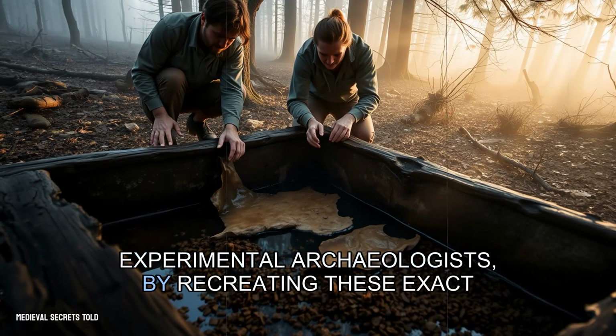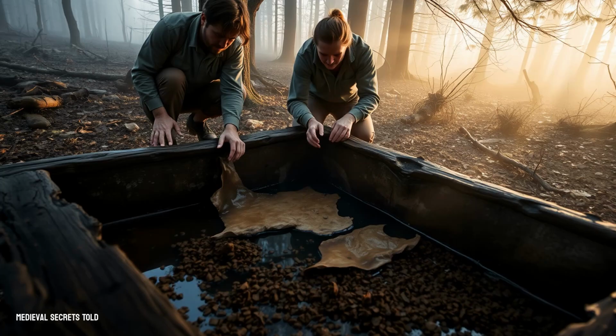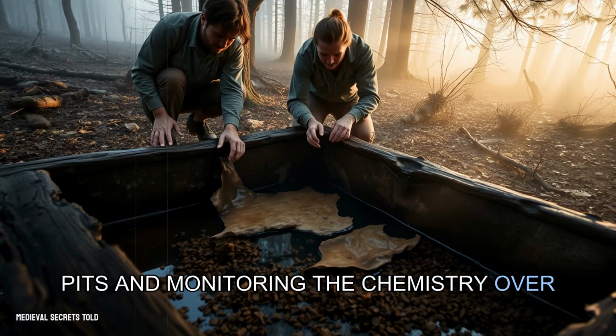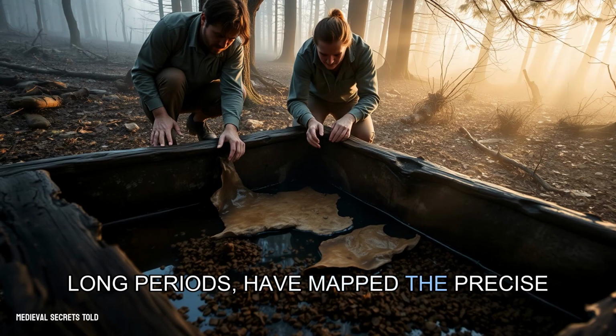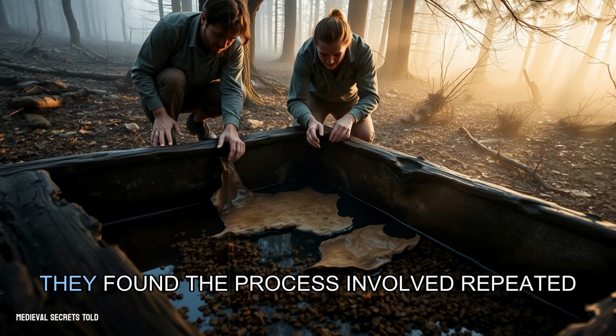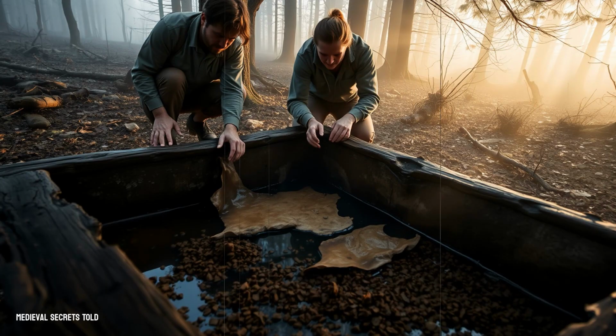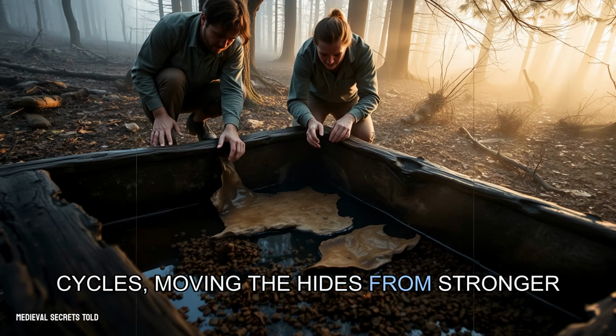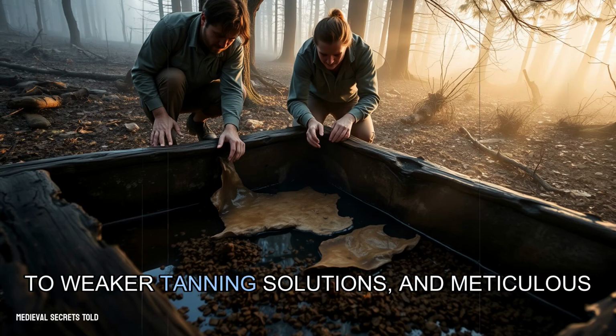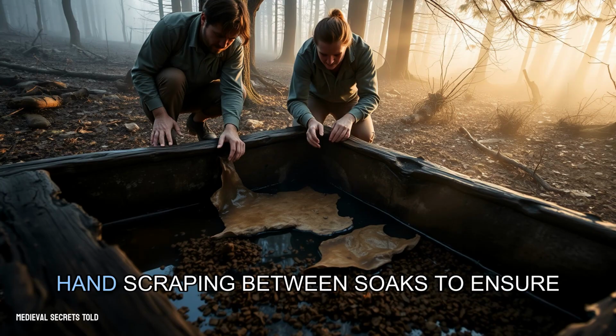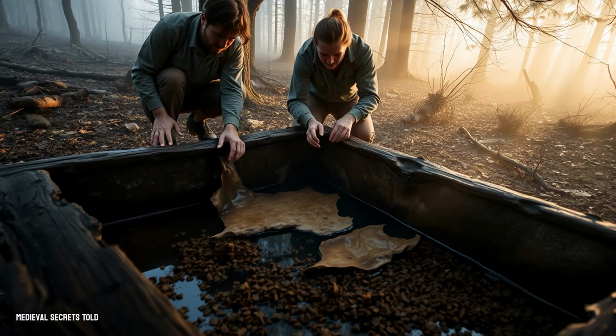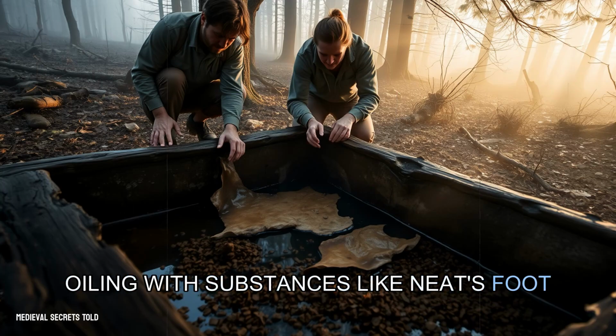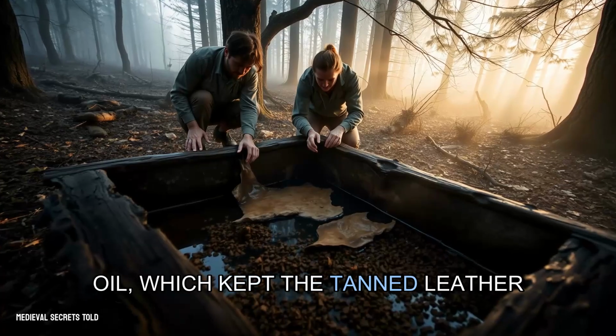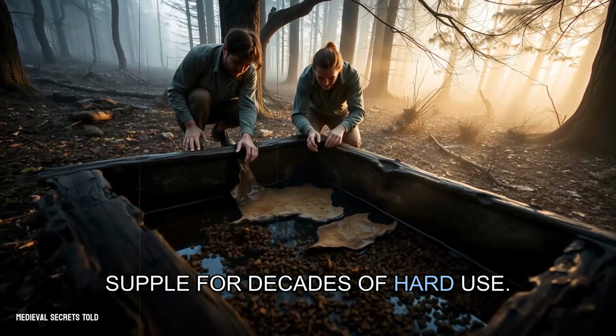Experimental archaeologists, by recreating these exact pits and monitoring the chemistry over long periods, have mapped the precise sequence. They found the process involved repeated cycles, moving the hides from stronger to weaker tanning solutions, and meticulous hand scraping between soaks to ensure even penetration. The final step was a generous oiling with substances like neat's foot oil, which kept the tanned leather supple for decades of hard use.